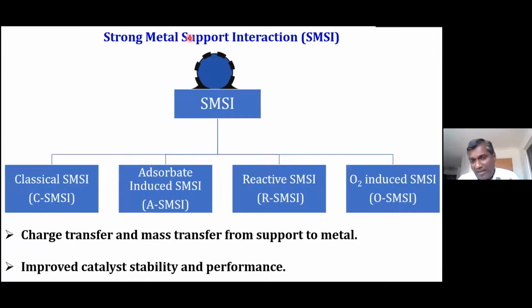Now, let's go to the next aspect of SMSI, or the metal support interaction, which is sometimes called a strong metal support interaction. There are a number of classes of this SMSI. This classical SMSI is very well known, reported by Tauster et al. sometime in the late 70s. They reported that when you have a metal nanoparticle of platinum group metals, and a support that can have variable oxidation state, what happens is when you reduce this catalyst at very high temperature, the support material forms a layer of this support oxide on the metal nanoparticle, and it completely covers that. So that is the classical SMSI.